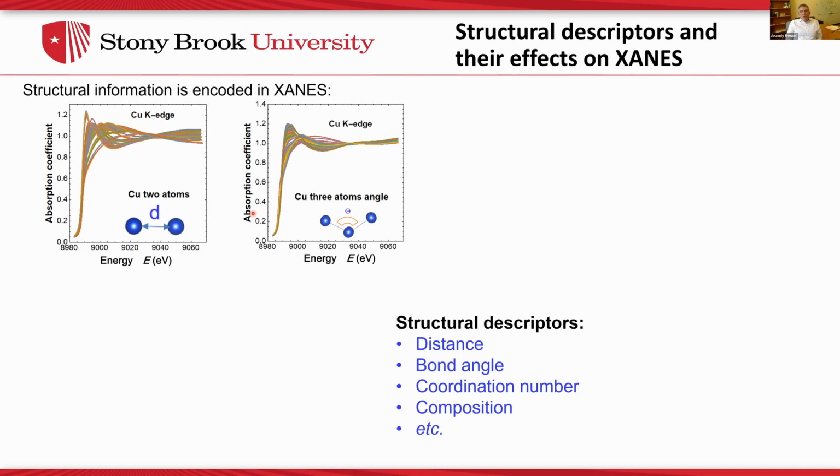That's why alloys are very useful, because in alloys, even if they're bulk, there are some interesting questions in the local structure, because the compositional motifs, even in the bulk, may range from homogeneous to heterogeneous. They range from positive short-range order to negative short-range order. These are very difficult to detect, especially in operando conditions. And XAS coordination numbers are key for measuring whether it's positive or negative short-range order. We can actually train a neural network to do that, and it doesn't require this site-specific training. We have a different approach, which I didn't discuss.